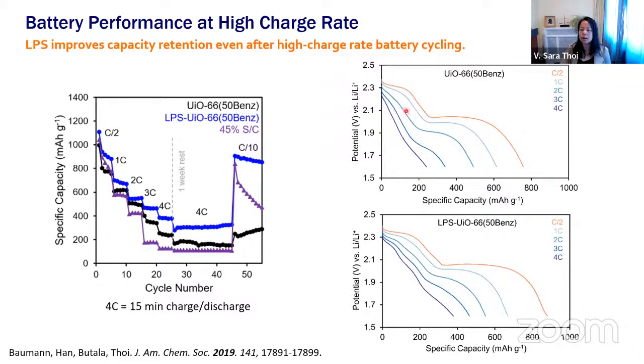On top here, you see that this is our UiO-66 that is unfunctionalized, whereas the bottom one is functionalized. And you see that there seems to be emergence of a secondary kind of plateau here that occurs at higher C rates. And we think that that has to do with the fact that thiophosphate binds to polysulfides that maybe shifts the equilibria of polysulfides within the pores of the metal-organic framework. We think this might be critical for battery cycling.